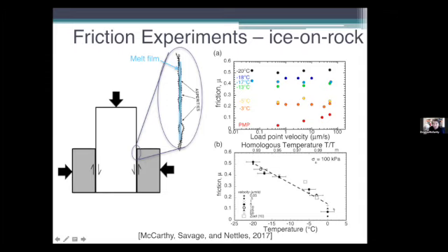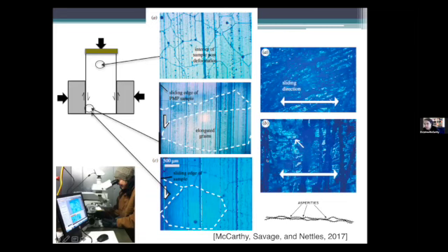We also looked at microstructures. Told you I really am interested in the microstructures. And so this is the cross section right here, right at the sliding interface. And for those samples colder than the melting temperature, we saw some elongation of grains or some growing of grains, but generally the edges looked almost identical to what the interiors looked like. So this kind of nice foam texture as we created them. But in those samples that were at the melting temperature, we saw these elongated grains that we know from past experience is consistent with melting and refreezing.